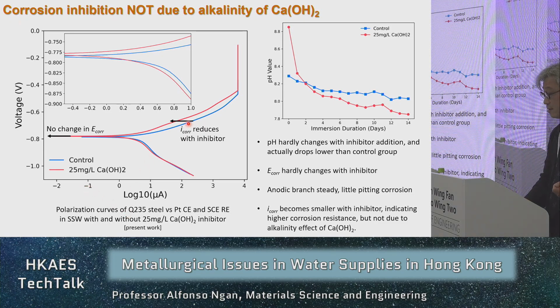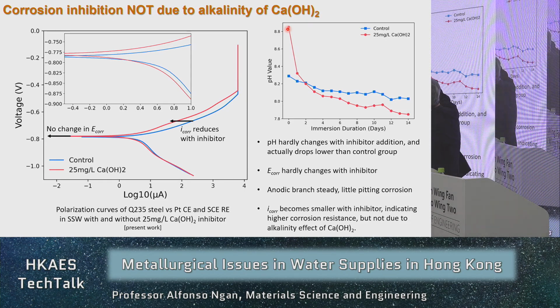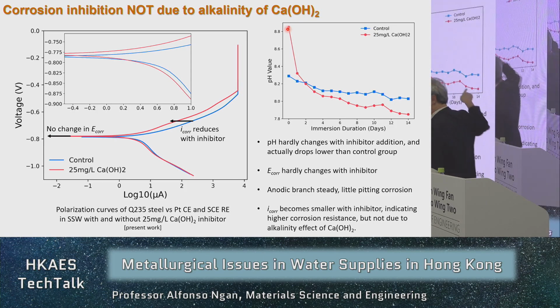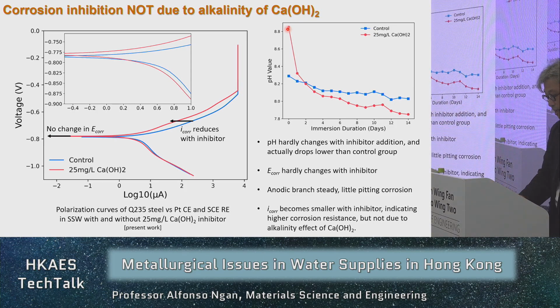All right, so this scale is largely magnified. It doesn't start from zero. Okay, so the control is that value, without adding the lime is that value. Adding the lime, of course, the pH will go up, but just by a very small amount. It goes up from 8.3 to 8.8 something, so point something pH, which is not great. And actually, for increasing immersion duration, the one with the inhibitor has the pH drops. Okay, so the pH cannot be a reason.